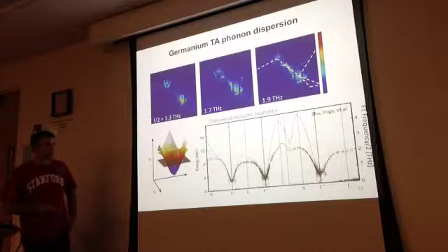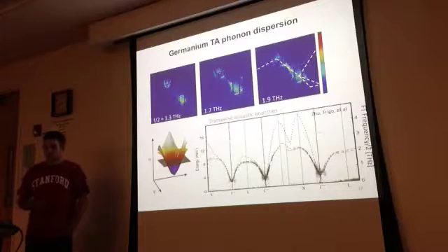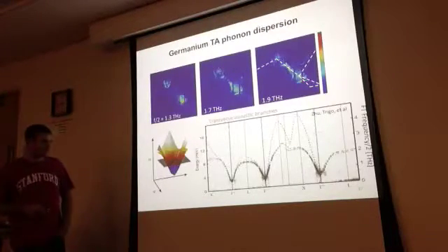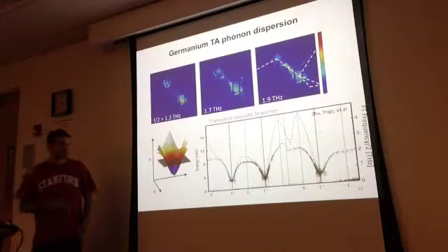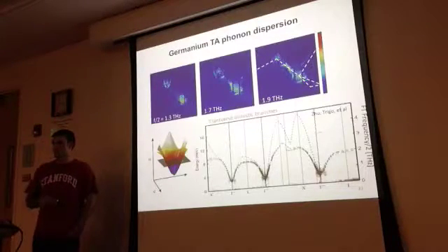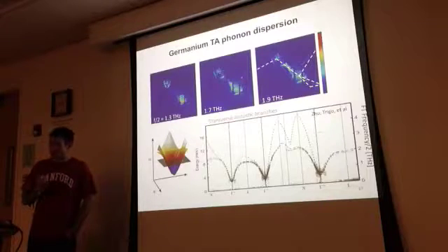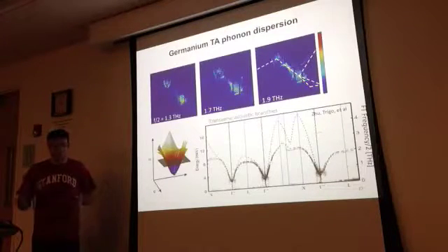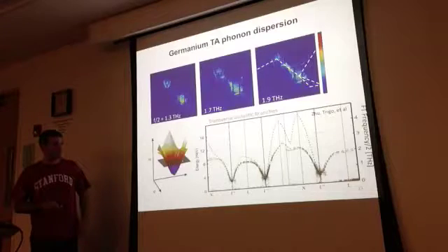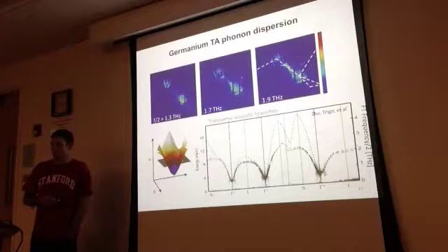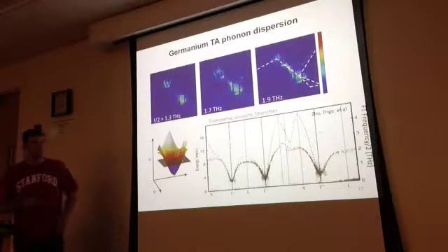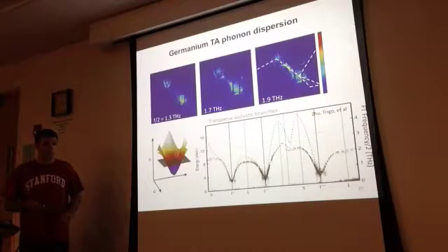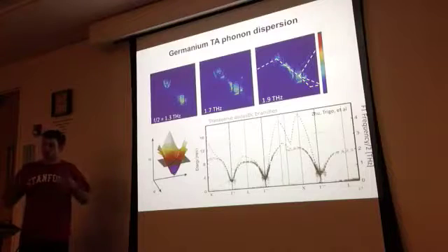So if you compare this to state-of-the-art inelastic X-ray or neutron scattering, we're already doing pretty good in comparison to the competition. To get these sort of dispersions with those techniques, you would have to collect statistics for literally days on end. And that's what they do. They have dedicated beamlines to scan for days on end. We took this data over the course of about 2 hours. And what really makes that possible is that since we're not looking at the energy shift of the scattered particles, we can collect many wave vectors at the same time because we don't need analyzers, and we can use the full bandwidth of the LCLS. We get the frequency resolution from the time-resolved dynamics.